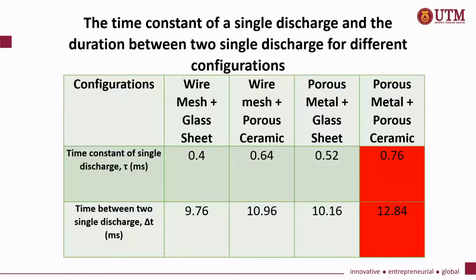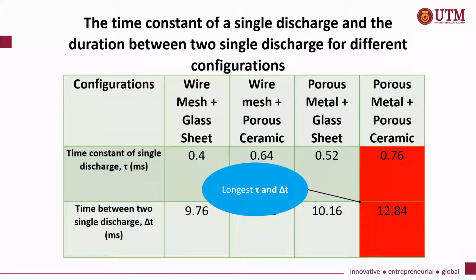From this table, it is apparent that the configuration with the porous structure material has the longest duration between single discharges compared to other configurations, while the configuration with the combination of wire mesh and glass sheet has only a 9.76 millisecond time difference between two single discharges. The time constant of each single discharge will be affected by the electric field strength and also the charge-up condition of the dielectric sheets.